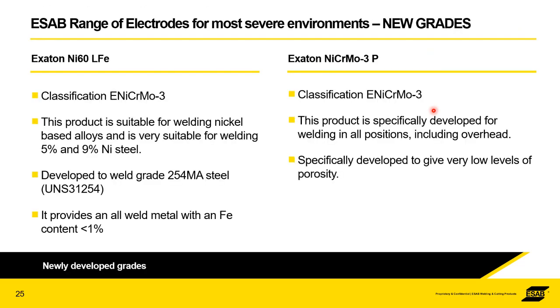And the last thing I'll leave you with are two brand new grades, as I mentioned. We've got an Ni60 LFE. This is a nickel chrome moly 3, alloy 625 equivalent, so it's 60% nickel. In the same way that grade is suitable for welding nickel-based alloys, 5% and 9% nickel steels, 254 SMO, the key with this is the LFE means it's low iron. So we've got an all weld metal content that has less than 1% iron.